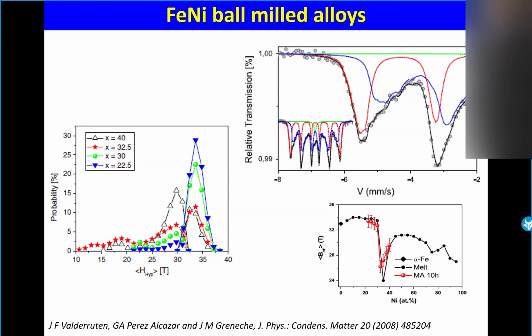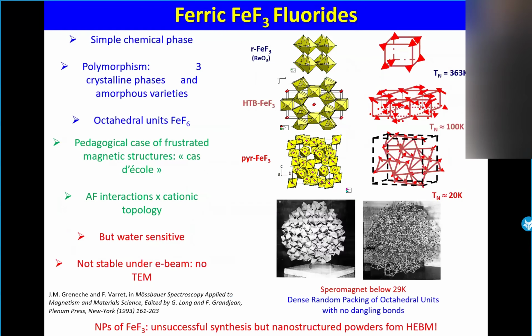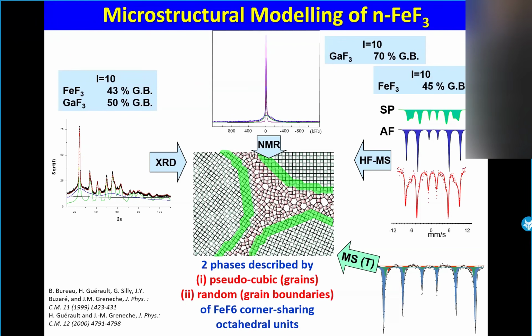So I come back to the fluorides. The idea now: I asked several times of colleagues, please, could you prepare nanoparticles of FeF3? But they were not able. Maybe I don't know if they were very motivated. But in addition, there is the problem that iron fluorides are not stable in air. Nevertheless, we prepared them by ball milling, and the idea was to store the system in a glove box, and to prepare samples in the glove box to avoid some evolution of the sample.